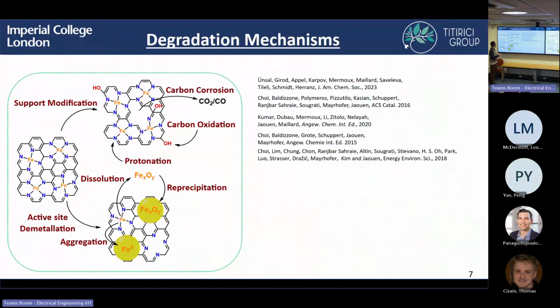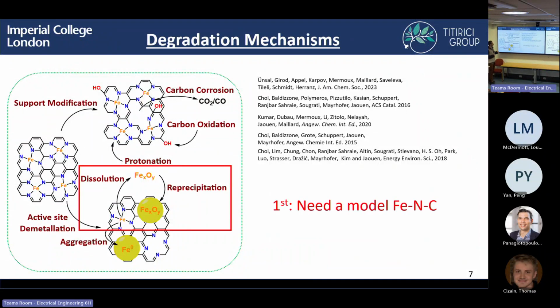And so these materials can degrade in many different ways. You can have support modification, so carbon corrosion, carbon oxidation. You can have protonation, or alternatively, you can have degradation of the specific active site, so you can have the iron dissolving or aggregating into nanoparticles. There's really a whole host of different ways that these materials degrade, and this is why they degrade so fast. But it's been found from the literature that there's a general consensus that the way these catalysts mainly degrade to begin with is from this iron dissolution mechanism. And so what we really wanted to do was study this further and understand what's going on.